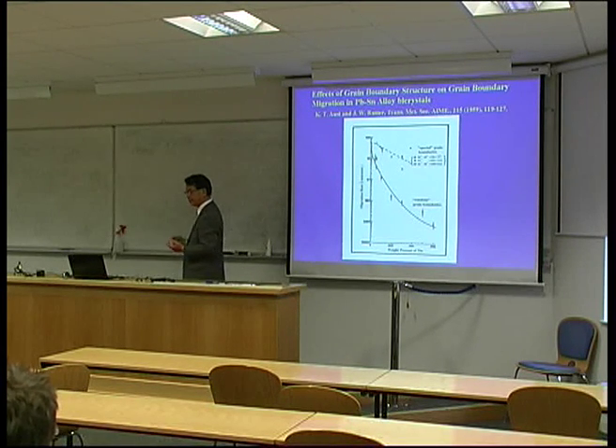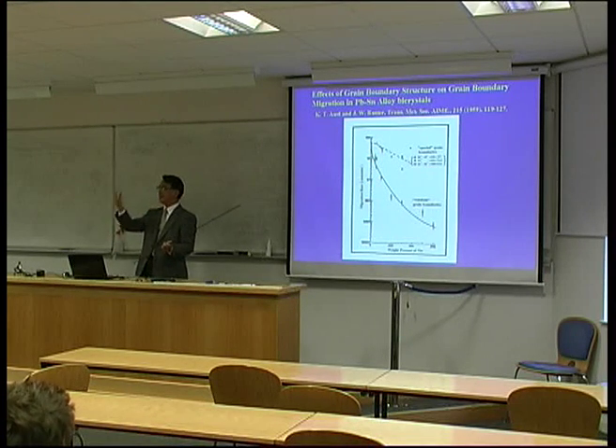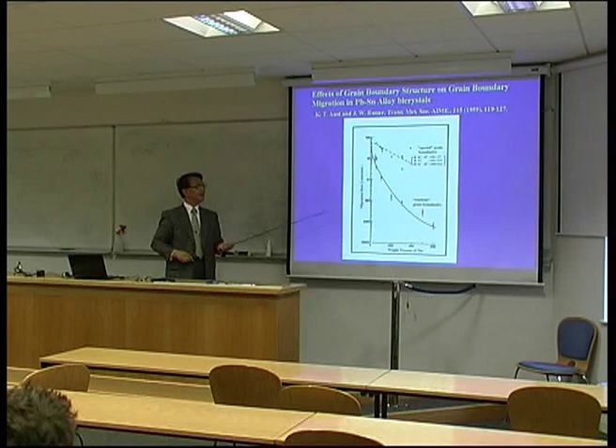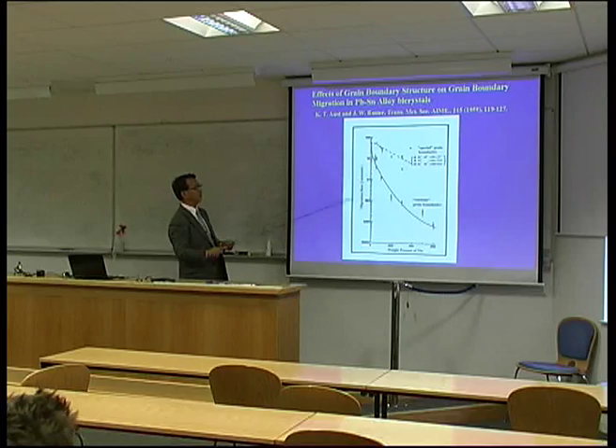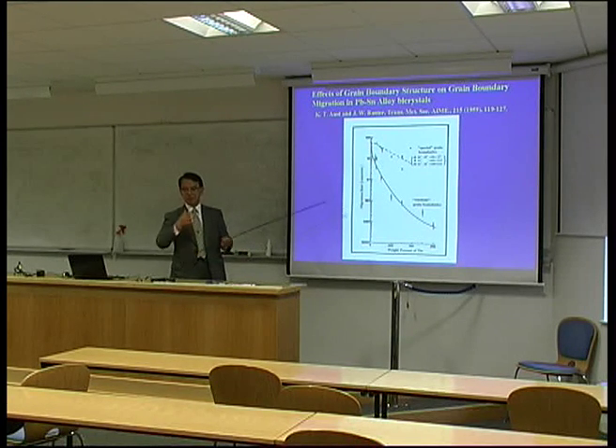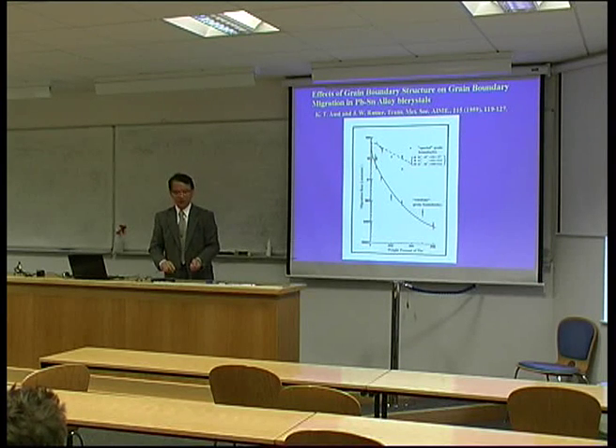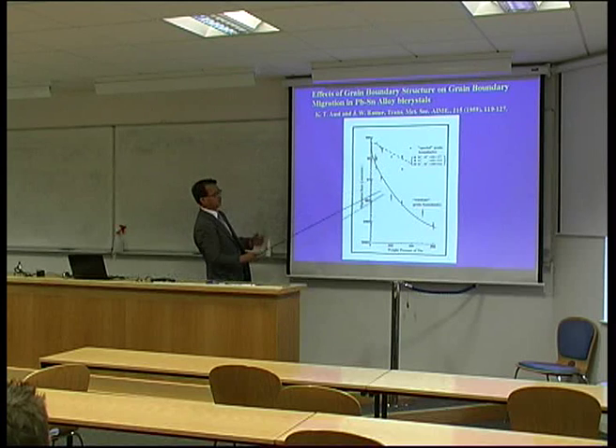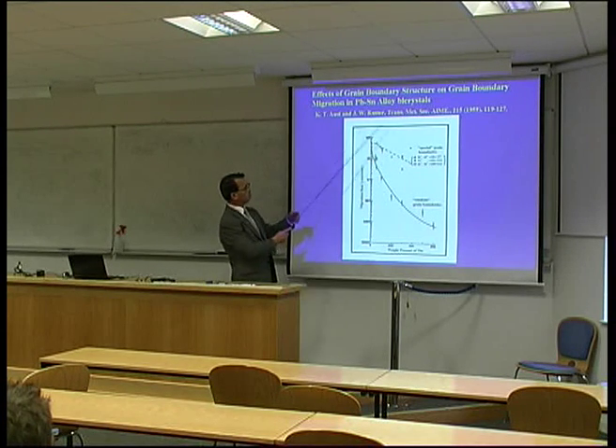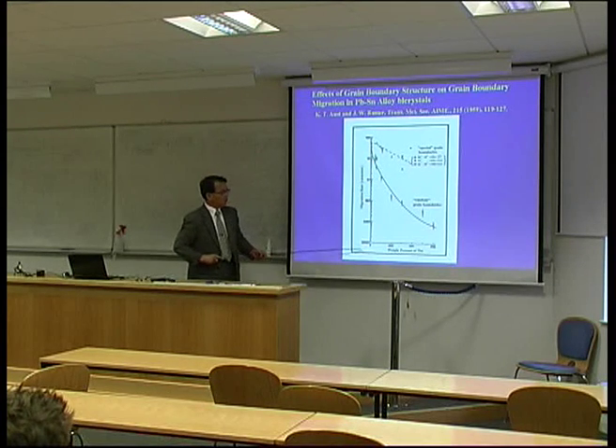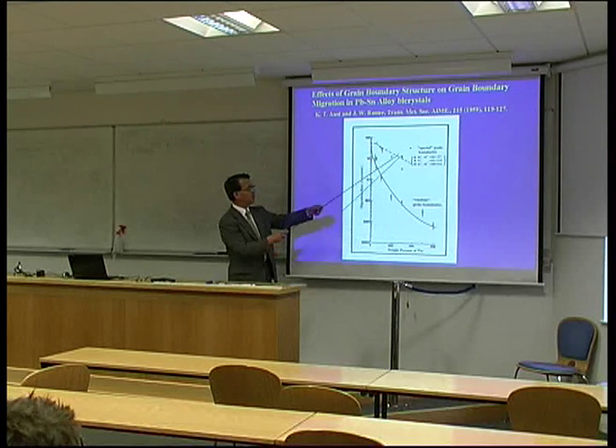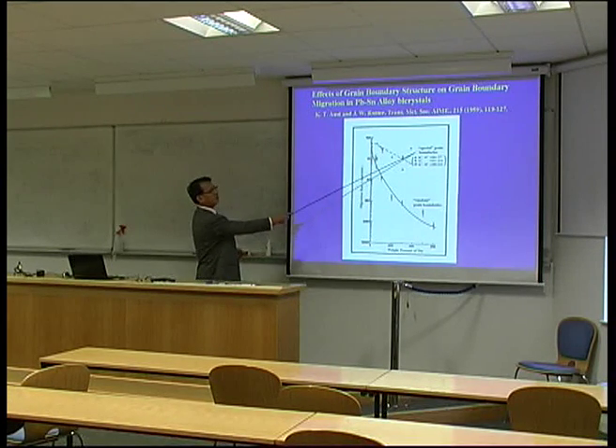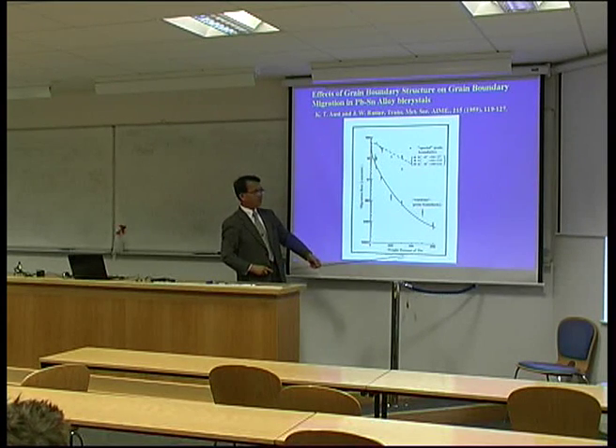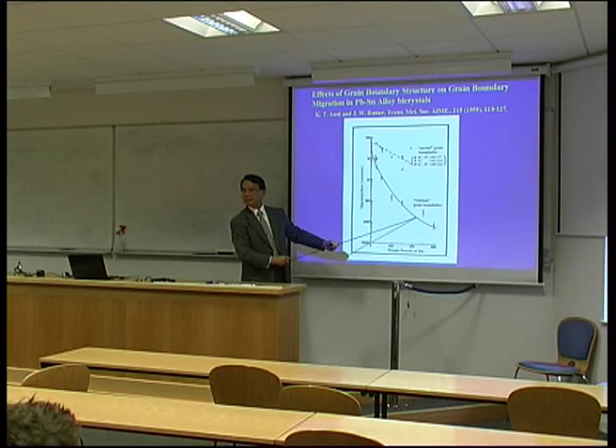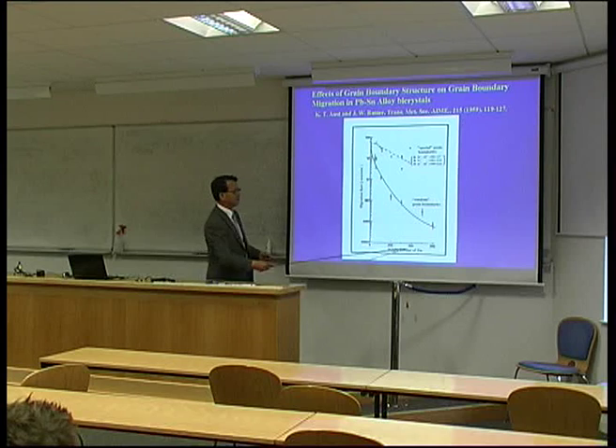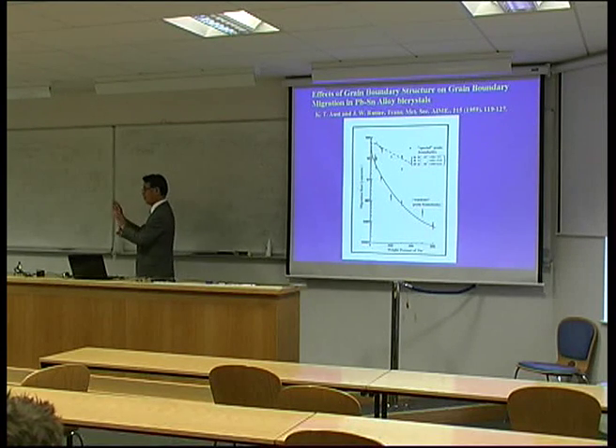And also, for grain structure formation and evolution, the very important key parameter is grain boundary migration, because during grain growth, boundaries have to move. So this is very basic knowledge. But again, in very old work from the Aust group, depending on the type of boundary, if you put in impurity, the boundary migration behavior is quite different. So special boundaries are not so strongly affected by impurity, but a high energy random boundary can be drastically affected, retarded very drastically. So there is such a big difference.